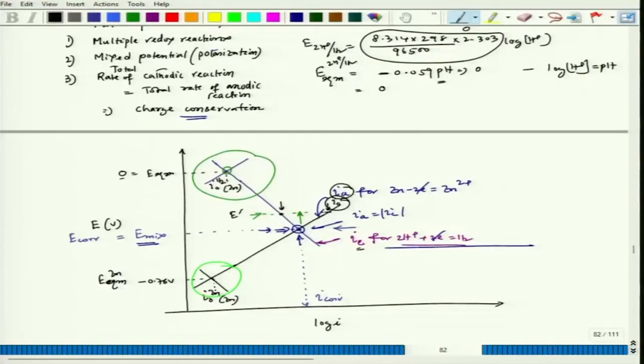So, now in this case, definitely if I go on the positive side, I would definitely increase my corrosion rate in the form of increase in IA. So, how can we reduce IA? Because this I corr is nothing but IA, which is the dissolution current density. Now, I could see that the current density, corresponding to IA, can reduce if we follow this line. That can be followed if we take the potential downwards from this reference potential.